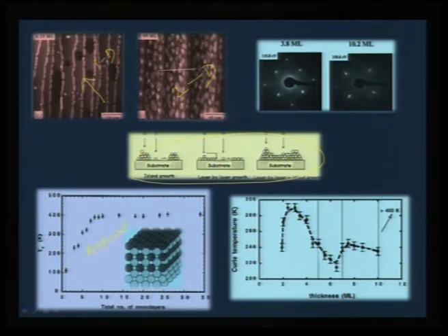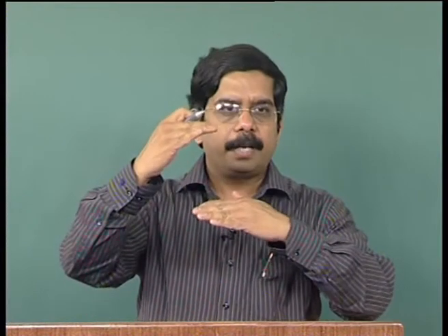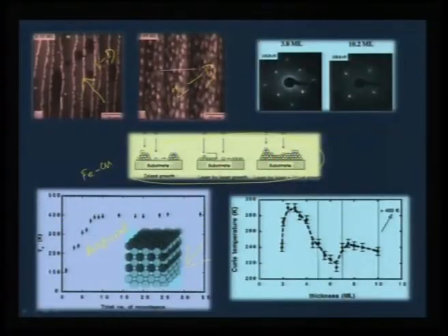artificial layers of two immiscible alloys. For example, iron and copper is the example that I have shown, how two elements which are not miscible at all can be made to form an alloy if you forcibly grow layer by layer two-dimensional layers. So this is one classic example where, if you start with just one atomic plane and keep on going, then you can get a bulk property somewhere around 8 to 10 monolayers. So this is a very grand demonstration of how you can control deposition on the atomic scale to realize unknown alloys which are not known in mother nature.